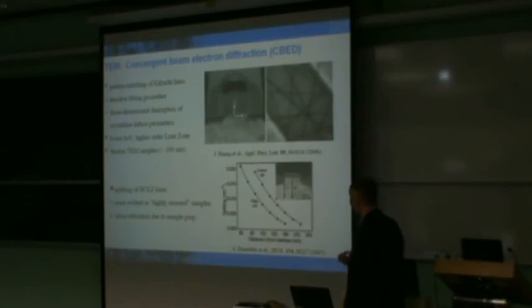The problem is that because you're dealing with a dynamic diffraction effect, what's been seen is that the splitting of these lines has been exacerbated by the fact that you have highly stressed samples, and a TEM sample is basically what you can consider a slab, and as you approach the edge of that slab, you have significantly more elastic relaxation. And so it's that non-uniform stress distribution through the thickness of the TEM sample that leads to some of these artifacts that have rendered it not as successful a technique. And so the two that I'll show that have been very well implemented are those that utilize diffraction.